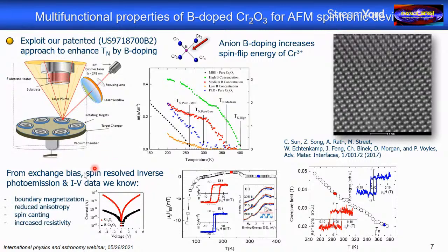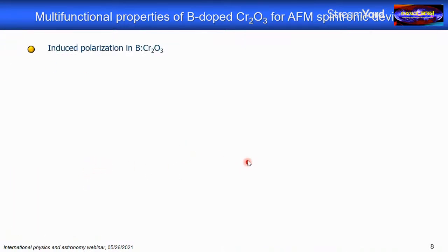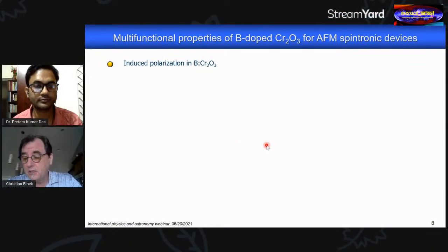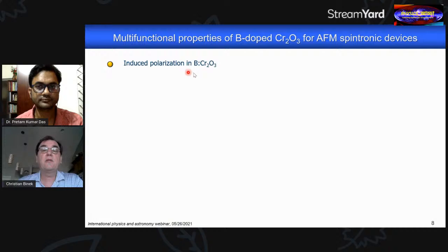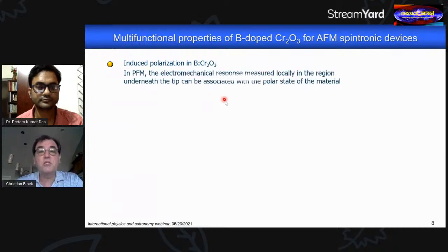So what's next? The next thing is that we observed, and that's not quite the historic pathway I show you now, but to make the story more coherent, I show you now that with the boron doping, some additional very surprising properties came up that we didn't expect. So it was not only that the system got a higher Néel temperature and that the anisotropy was slightly modified. We found something very interesting, namely that this material can have very large electric field induced polarization.